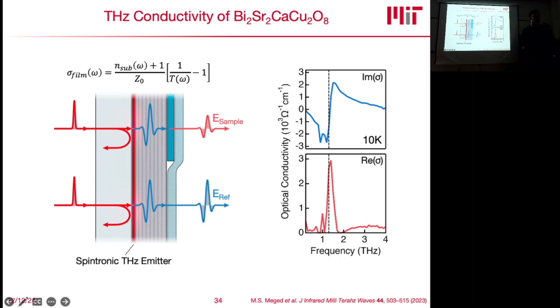So this is the Lorentzian. That means it is a collective mode of this material. It's a very, very strong mode. And in the imaginary part, you get this very nice derivative line shape, which corresponds together. These are Kramers-Kronig related properties. However, since we're measuring amplitude and phase, we get both of them at the same time, so we don't need to do any fancy transformations.